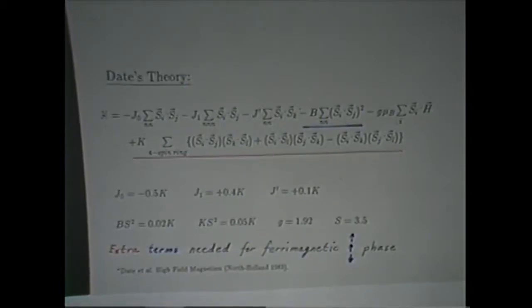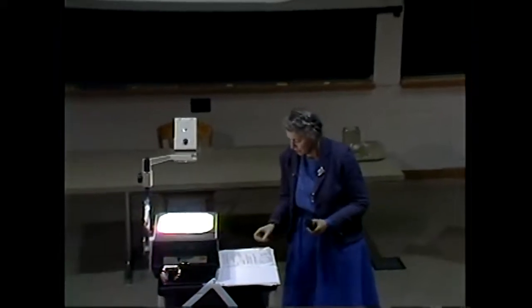These things had been predicted, but there had been no real observations. But for this system, in order to get the ferrimagnetic phase, the one with the two spins up and one spin down, it's necessary to have the terms in the blue and the red. And that was a new piece of physics. The reason they're so big is because we have spin seven-halves. Europium, you know, is a half-filled shell, and that makes it kind of interesting.